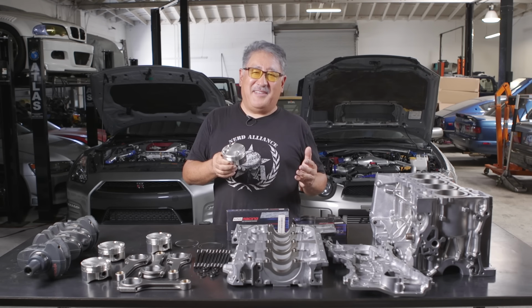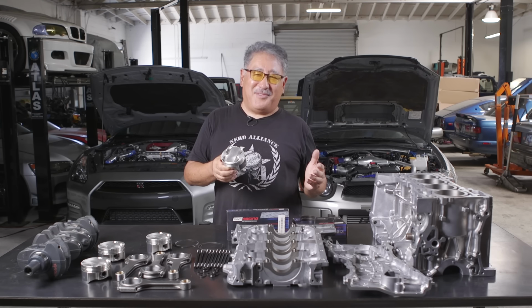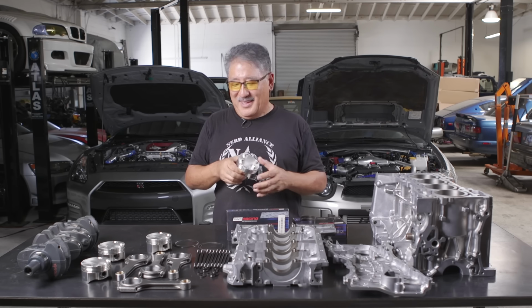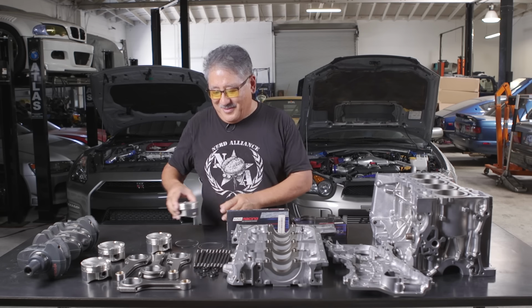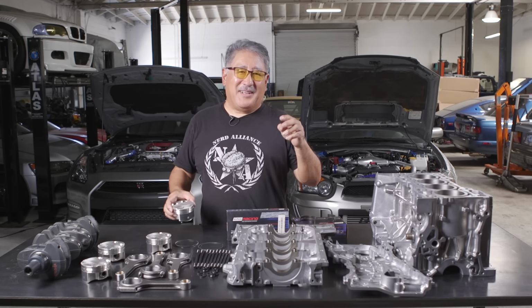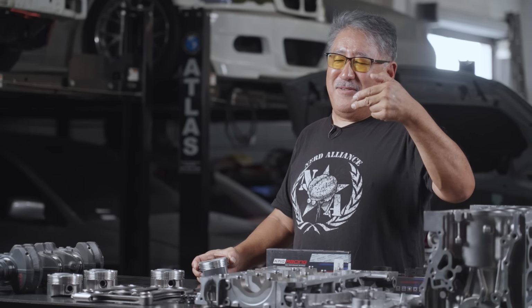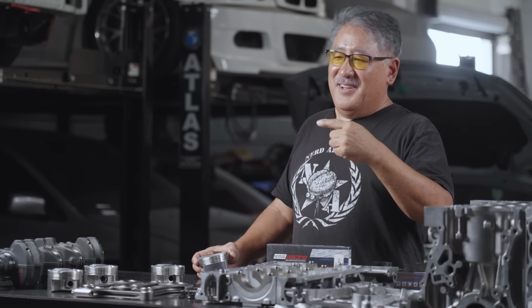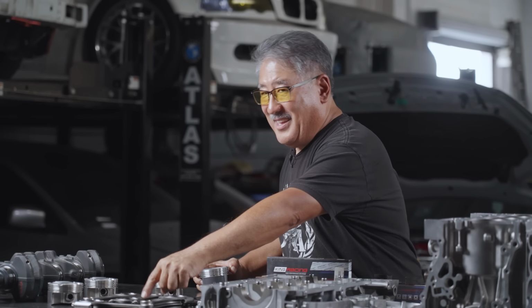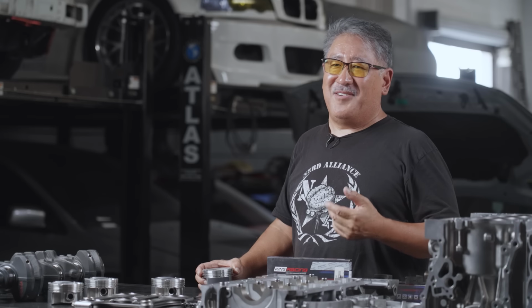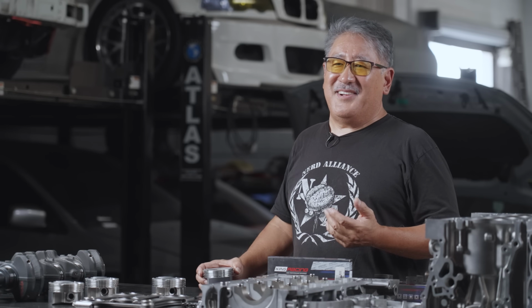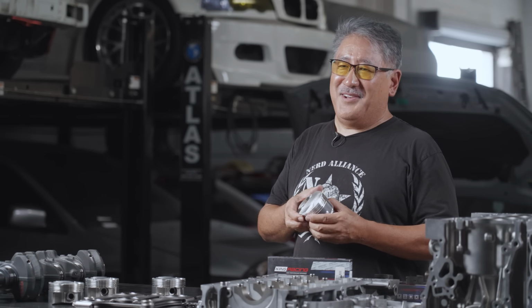A lot of times in the past, a tapered wall tool steel pin was the hot tip, but we've found that as motor output has gone up more and more, a tapered wall pin wants to flex under load, and that tends to catch on the small end bushing and spin it out of the rod. And that is not good and usually causes catastrophic failure.